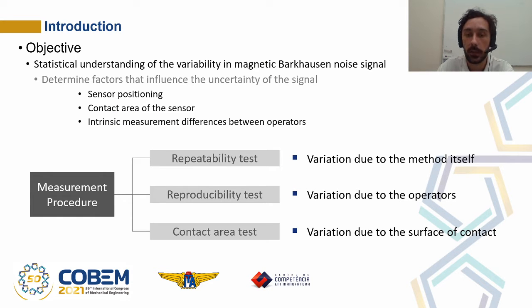The statistical understanding of the variability in the magnetic Barkhausen noise signal, which is sensitive to the stress state and hardness of the material, is capable of providing a non-destructive method for a comparative evaluation of the residual stress state in steel samples. The objective of the present work is to determine factors that influence the uncertainty of the signal, such as the sensor positioning, the contact area of the sensor, and some intrinsic differences between operators when measuring.